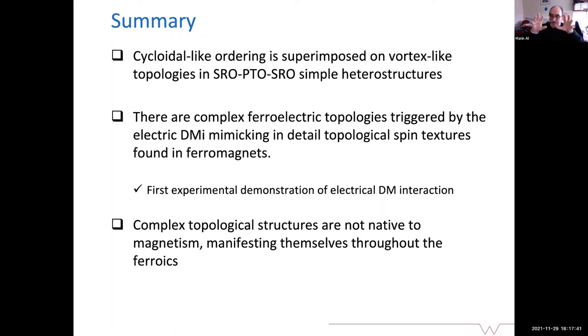Now, you have to see that the polarization is not an atom-related property. It's a property of a unit cell, of the entire symmetry. So if you change the arrangement of the unit cell, then you change the polarization direction. Now, if there is a twisting or a kind of rotation of the oxygen octahedra within that unit cell cage, the polarization follows.